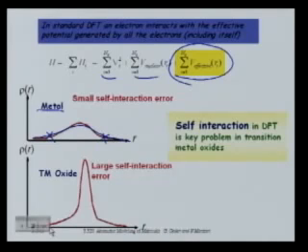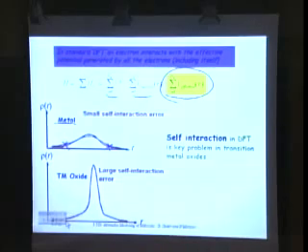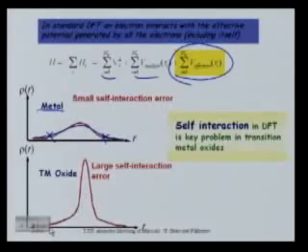If you put an electron in a delta function, if you didn't have an uncertainty principle, and you calculate its potential, it's basically sitting on top of itself. You'd have an infinite self-interaction. So the more local the state is, the more self-interaction you have. And the exchange correlation functional can't quite correct these two in the same way. And remember that the exchange correlation correction comes from homogeneous charge densities. So it tends to correct the metallic state better than the localized state.